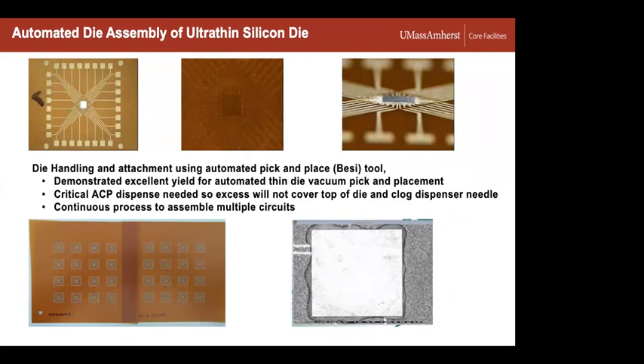If you look at typical printed circuit boards, or even printed circuit boards now that are migrating to flex, you still have a lot of components that are fairly thick. They're much thicker than the substrates themselves, and they still stick up a lot, and you still need to encapsulate them if there's any type of environment where they might be impacted or further abrasion on something, and so on. And so basically there's an interest to thin the silicon die, forego the packaging, and directly assemble this and put it using a conductive adhesive onto the flexible substrate.